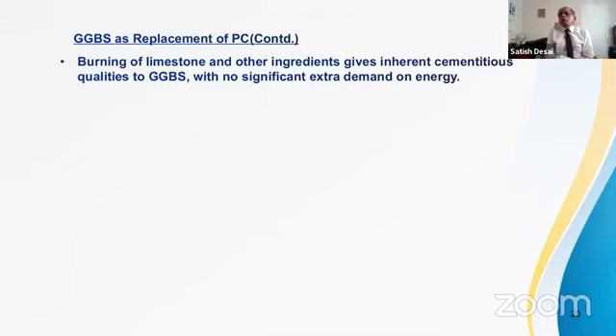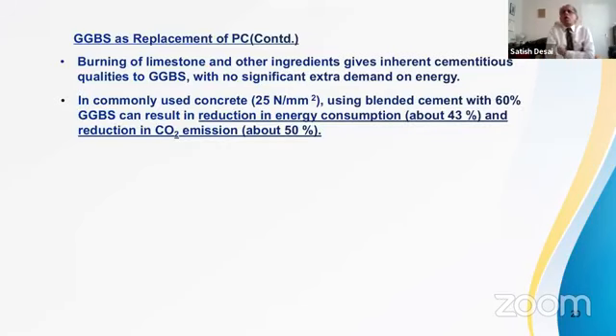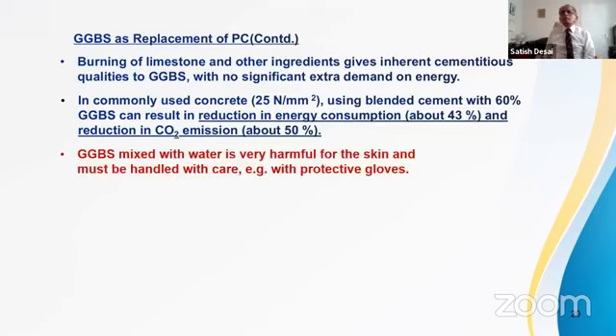Burning limestone and other ingredients gives inherent cementitious qualities to GGBS. We are making use of most of the energy that you would have used to make iron, but GGBS is the byproduct. In commonly used concrete of 25 newtons per millimeter square, blended cement with 60% GGBS gives us a reduction in energy consumption of 43%, reduction in carbon dioxide emission about 50%. Good figures, I'll say, but the mixture of water and GGBS is harmful to the skin, so the operatives have to take care, use protective gloves, etc.